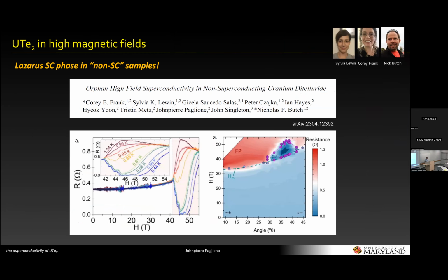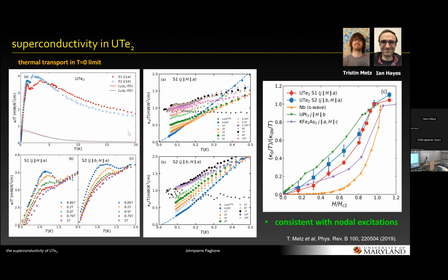So there's a recent paper by Yuji Matsuda's group, claiming to redo this experiment on the higher TC samples and showing something that looks like this niobium curve, and claiming that it is indeed fully gapped. We're trying to finish a paper basically showing that if you go to low enough temperatures and you do your extrapolations properly, it looks very much like that, but it actually looks more like this potassium iron arsenic behavior, where this increase with magnetic field is suppressed quite a bit, but there is a finite value and it rises pretty rapidly at low field. So it is consistent with a nodal order parameter, even the 2K. Or something very close to that, I guess. Something that has low energy excitations, yeah.